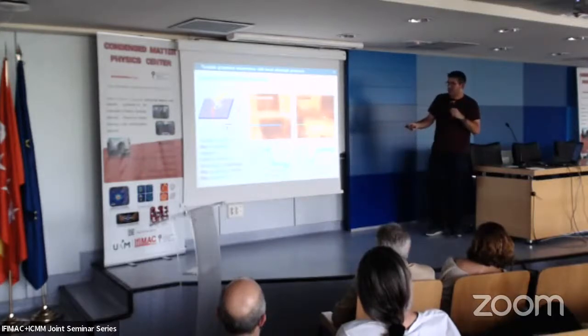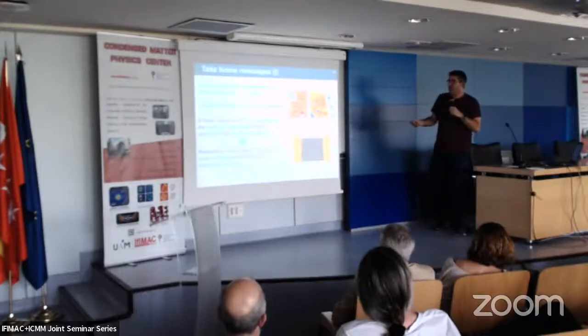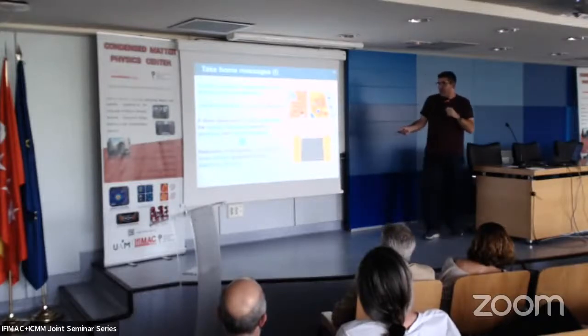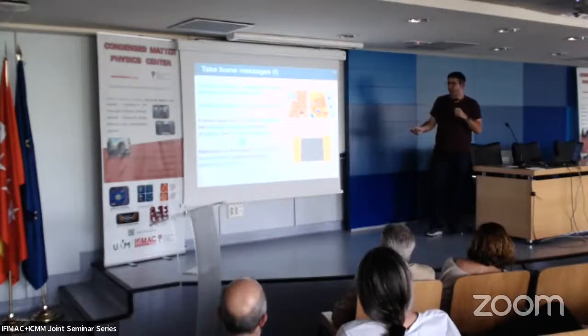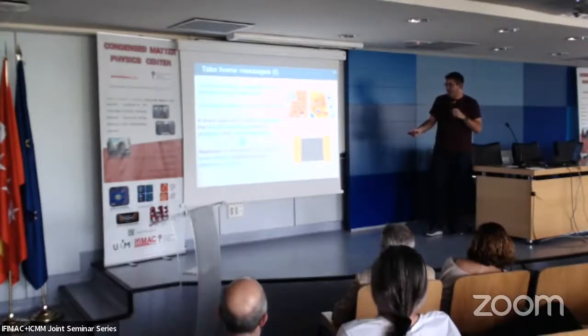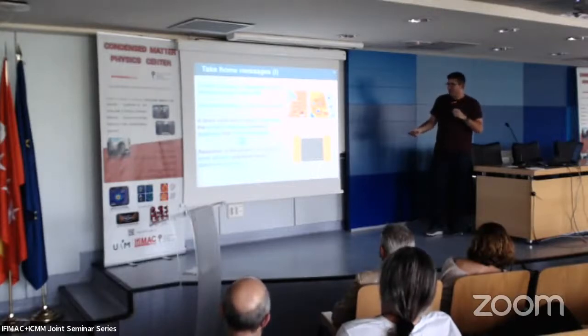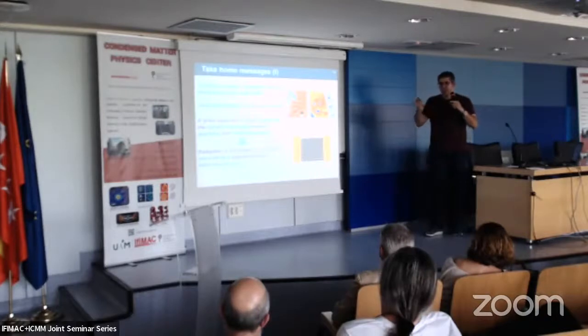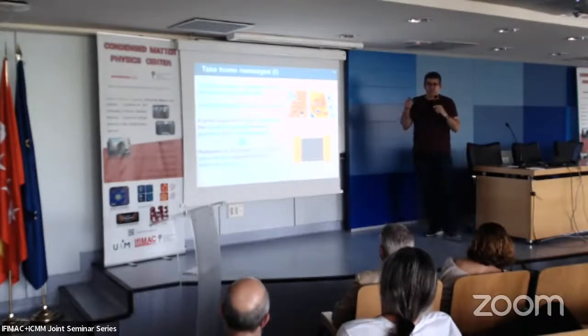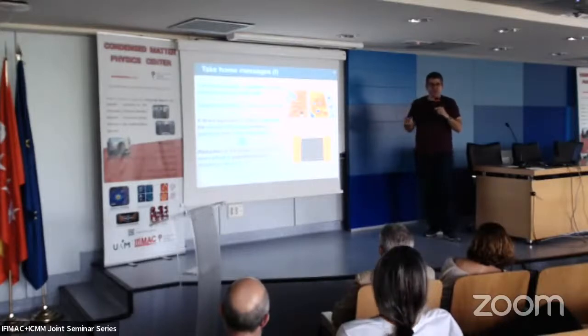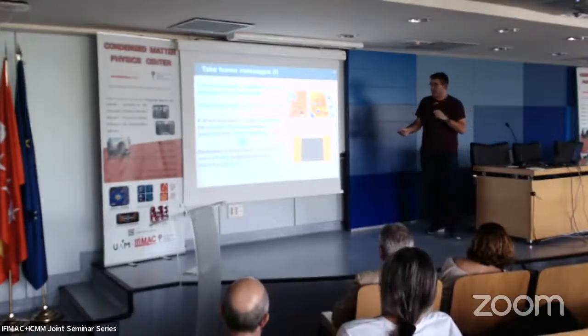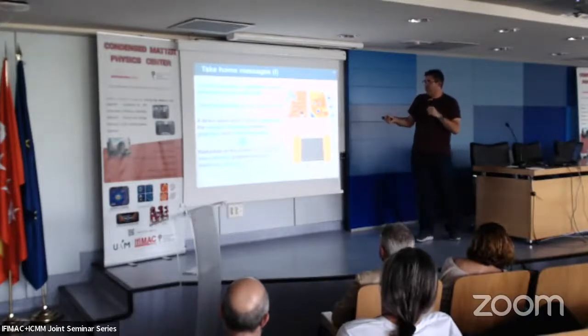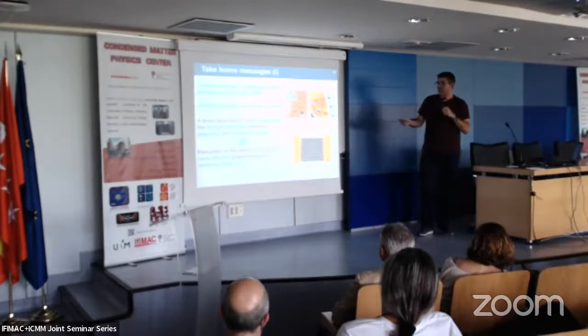And this is telling us that in these areas, the contact resistance with our metal is lower than in pristine graphene. And this is something quite important because we now go to the take-home messages. I go to the last one before. If we can locally improve this contact resistance with a metal electrode, this means that we can put our metal electrodes in a future graphene device on silicon dioxide and modify the graphene before, in order to have a better contact resistance. In that way, we will lower the voltage we need to get the same current. This way, we could get more efficient devices, for example. The other take-home message is that we were able to locally fabricate areas with tunable p-doping, and we found that chemical bonding is the main responsible for this.